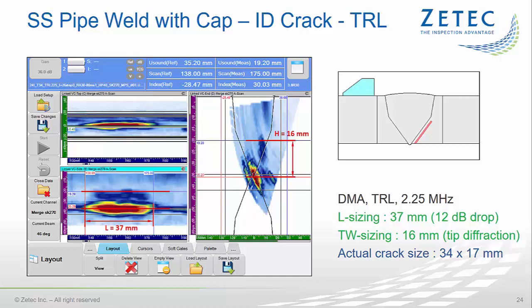The tip diffraction technique is known to provide the most accurate through-wall sizing results on cracks. The reference cursor is positioned at the center of the corner trap, and then the operator needs to examine the signals above the ID surface in more detail. Tip diffraction signals typically have much lower amplitude than the corner traps, so we need to apply some soft gain. As we do that, we can see several parts of the crack edge lightening up.